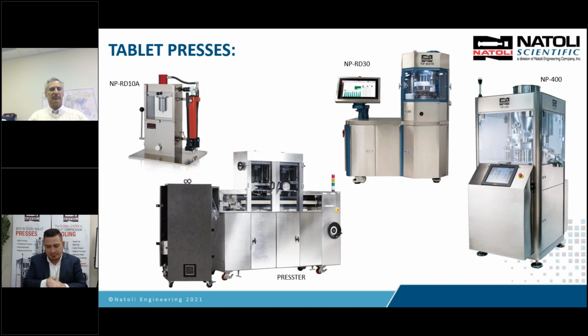At this part of the event, I'm going to talk about the RD30. We then took that material and we ran the RD30 and we did tabletability studies and we did strain rate sensitivity studies. These are very important studies that we want to perform at R&D stage to find out the failure points of our material. Too low of a pressure, too high of a pressure. What happens? We see capping, lamination issues, disintegration, dissolution issues. We see sticking issues.